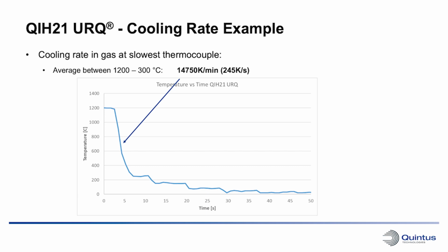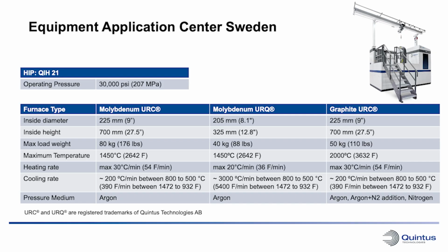Wow. So what kind of metals are using that kind of furnace? Low alloy steels require very high cooling rates. Aluminum, if you want to perform a T6 treatment, also requires very high cooling rates. Some nickel-based super alloys can require that as well. Okay. And then the other furnace you haven't mentioned yet, the URC furnace, what's that, the uniform rapid cooling? Yes, that uses the whole space in the vessel that you can use as a hot zone for your parts. And the cooling rate is a little bit slower compared to the URQ.